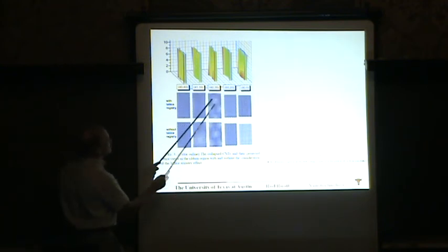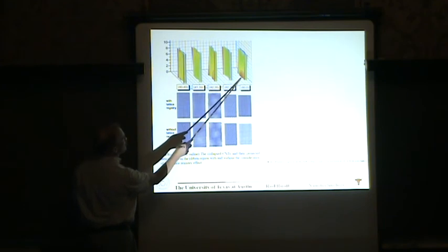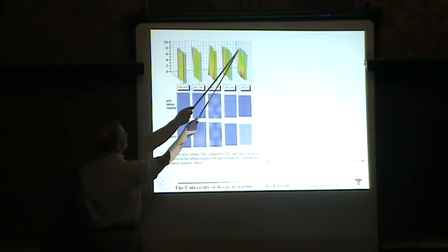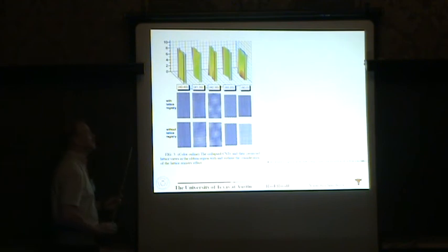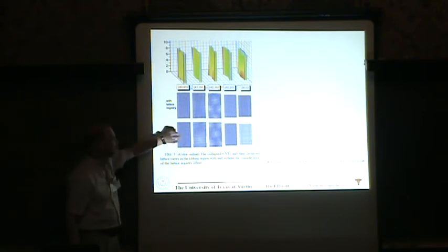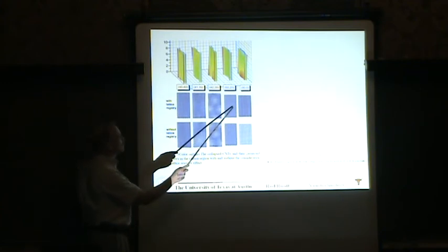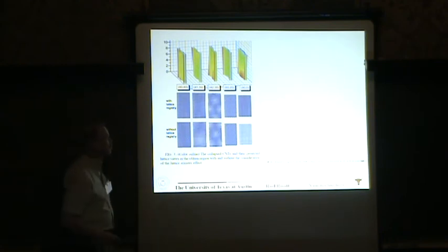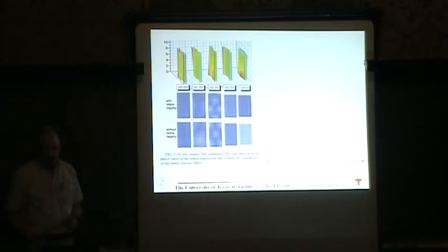And if you look at the zigzag tube, you can actually see that it's bulged outward here and in the opposite direction here. And you actually have that if you were walking along a twist. Okay? And here we're seeing the moiré patterns where, of course, with armchair we have just the AB stacking. And then for these other sorts of configurations, you have other sorts of patterns in terms of the interlayer registry.